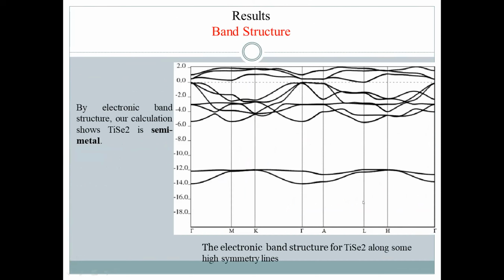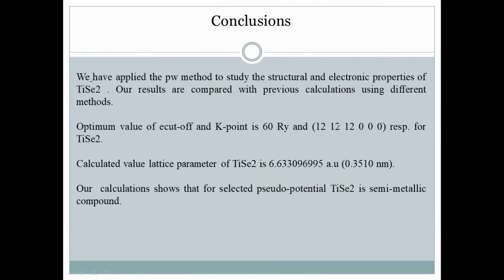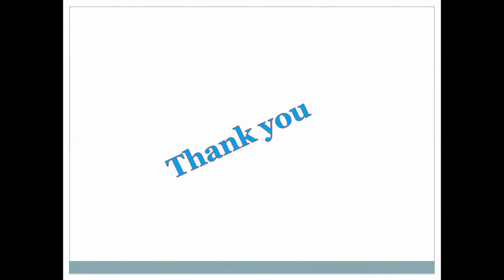This is the band structure diagram for TiSe2. If we look at this band structure diagram, we note that in TiSe2 the valence band and conduction band are just touching together. So we can say that TiSe2 is a semi-metallic material. So, for conclusion, we get E cutoff of 60 Rydberg, K points 12, 12, 12, and 0, 0, 0 respectively. The optimum value for the lattice parameter is 0.351 nanometer, and TiSe2 has semi-metallic properties. This is all from my side. Thank you, sir.